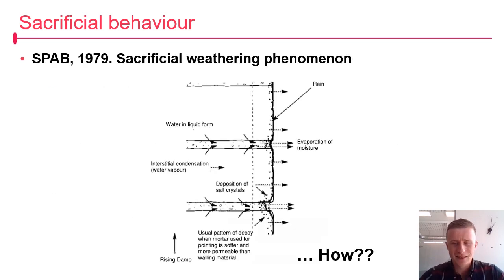Now, the SPAB had a key insight into this. That's the Society for the Protection of Ancient Buildings. In 1979 they published their findings on observations of masonry structures as they dried after periods of wind-driven rain. They noticed that the lime mortar joints appeared to soak the water out of the masonry units and into the lime joints, where the bulk of evaporation took place, and then lo and behold, that's where the salt crystals were deposited. The Eureka light bulb went on, the penny dropped, and this was dubbed the sacrificial weathering phenomenon.